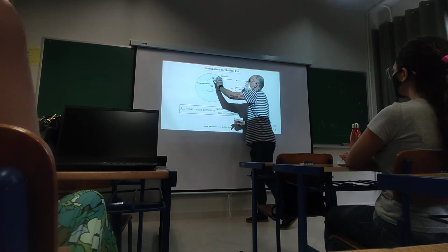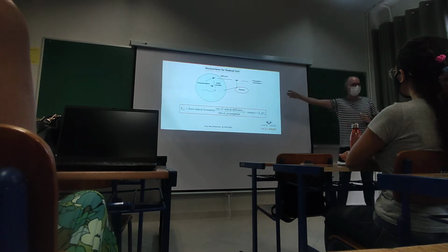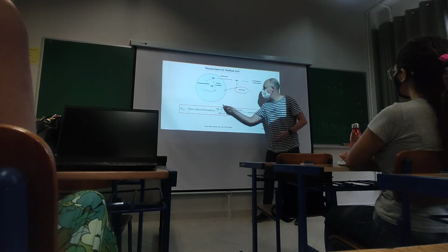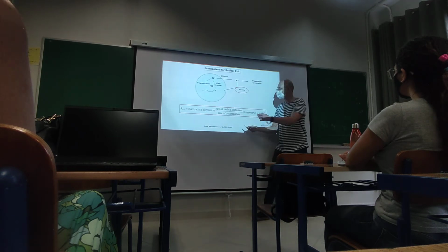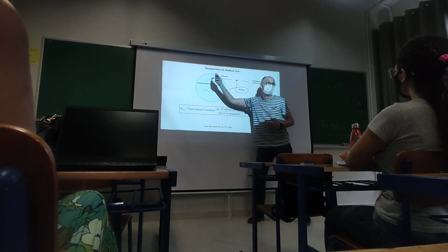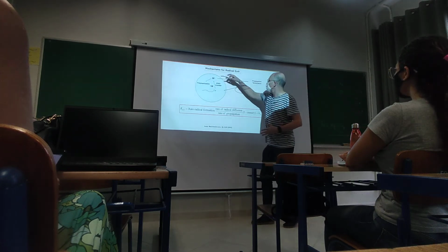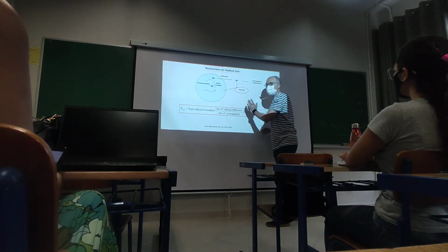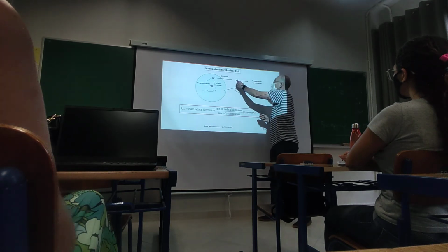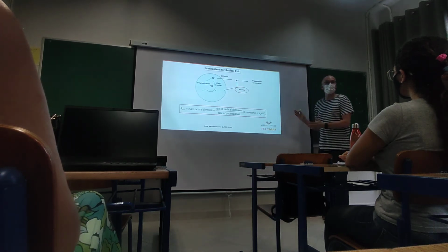So you will have to take into account the probability that this monomeric radical exits. So the rate of exit will be the rate of formation multiplied by the probability of diffusion, which is the rate of radical diffusion divided by the rate of propagation, because it's the main mechanism, the fastest mechanism. Once the radical exits, this radical can also re-enter this particle or other particles surrounding it.